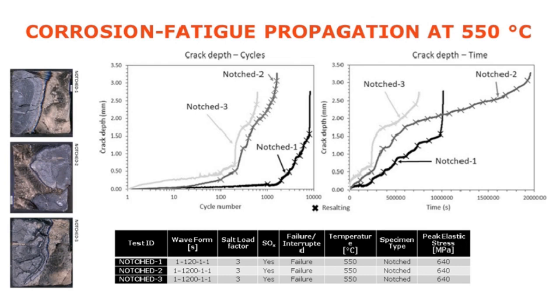If we start by looking at the crack depth per cycle, the plot on the left, we've got three tests: notch 1, notch 2, and notch 3. Notch 2 and notch 3 are a longer dwell again than notch 1, so they have more corrosion going on per cycle. And we can see that reflected in the fact that they take fewer cycles to fail than notch 1. So more corrosion, fewer cycles to fail. Again, that same story coming through.